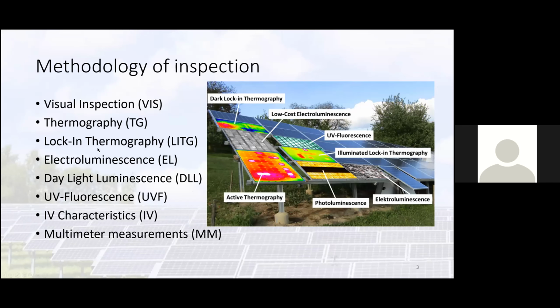Here is listed visual inspection, which is very common. Thermography, which is thermal imaging. Lock-in thermography, which is the same thermal imaging, just you have to have some synchronization between taking the photo and exposing it to the environment. Electroluminescence is a technology used in reverse on the elements of a solar panel, with current switched on, and it works like an LED, where you expose infrared. Then there is daylight luminescence, the same but during daylight. Then UV fluorescence, IV characteristics, which means current and voltage characteristics, and the most common one is multimeter measurements.